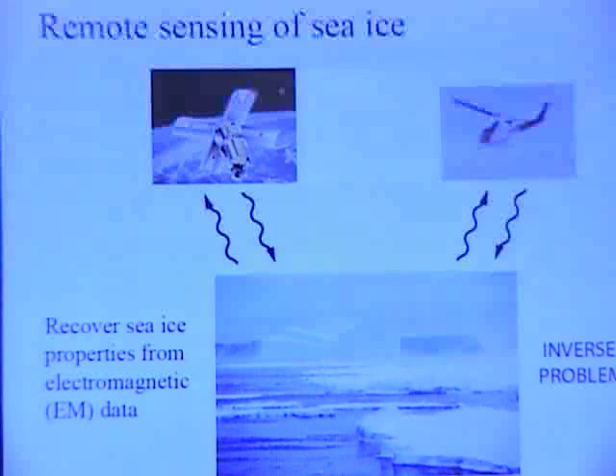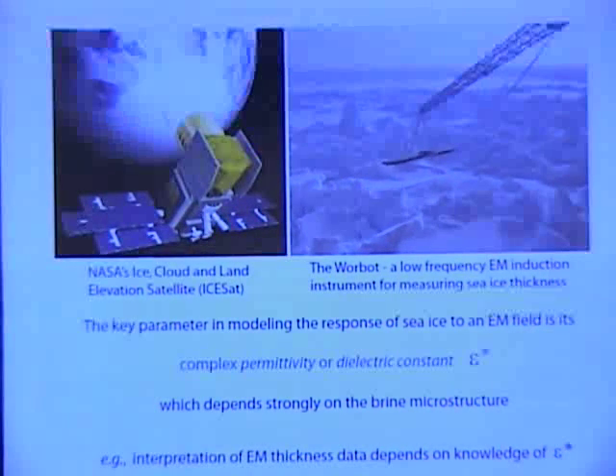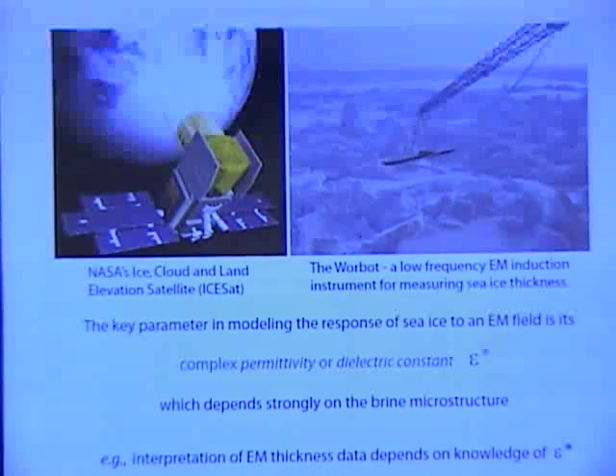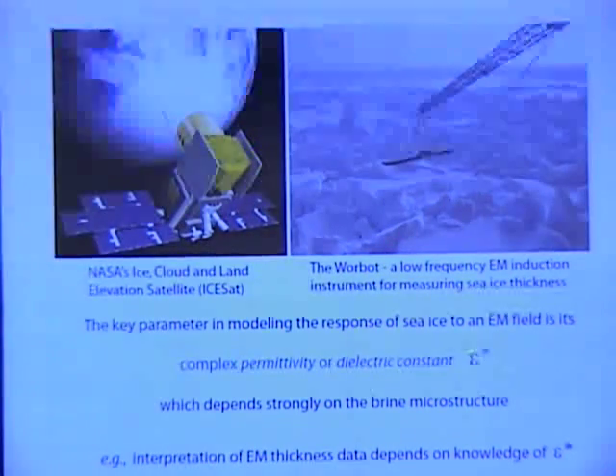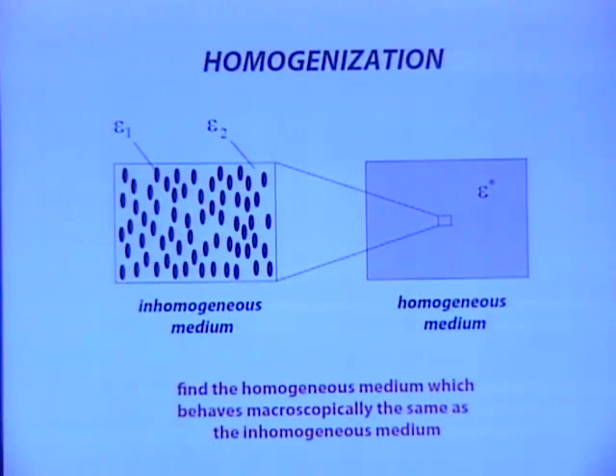Now a bit about remote sensing, how we're trying to electromagnetically monitor these kinds of problems. The key parameter in modeling the interaction of an electromagnetic wave with a composite material is the so-called effective complex permittivity or complex dielectric constant, epsilon star, which depends strongly, in this case, on the brine microstructure. And this is, again, an example of homogenization, where we have an inhomogeneous medium, and the whole idea of homogenization is to mathematically construct or find the homogeneous medium, which behaves macroscopically the same as the inhomogeneous medium. It involves solving partial differential equations and a lot of other kinds of mathematics that we employ in this business.